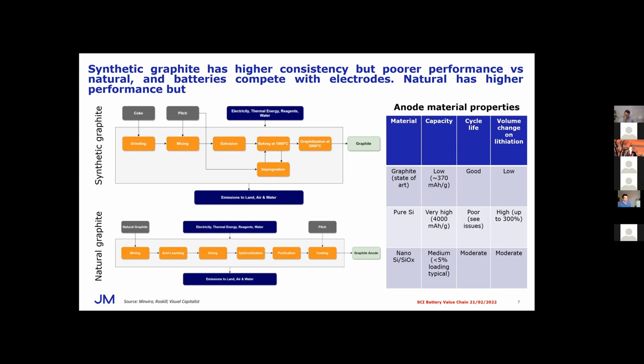Where we've seen a lot of interest and commercialization in recent years is the addition of silicon. Silicon in comparison to graphite has a very high capacity, more than tenfold. However, upon lithiation, it swells. And of course, in a tightly packed lithium-ion battery, this can be problematic. So where the research has tended to focus is trying to effectively prevent silicon from expanding. Here we see the use of nanomaterials and silicon oxide coatings, but the loading is quite small, maybe 5, now coming up to 10 or so, 15% of the natural graphite loaded with silicon, and that gives it a small performance boost, but does have some impact on cycle life occasionally. So it may not be such a robust material, a downside to the improved capacity that it creates.